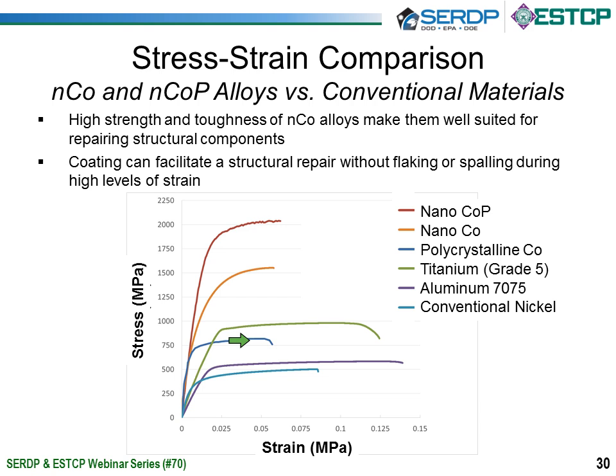Now, when you decrease the grain size of the cobalt to, say, 20 nanometers, you get an increase in strength to over 1500 MPa. And then when you further alloy with phosphorus, you get a further increase to over 2000 MPa. So this shows the benefit of reducing the grain size as well as solid solution strengthening with the phosphorus. But the other main point to look at is that the ductility hasn't changed. So we're still getting over 5% elongation before fracture.